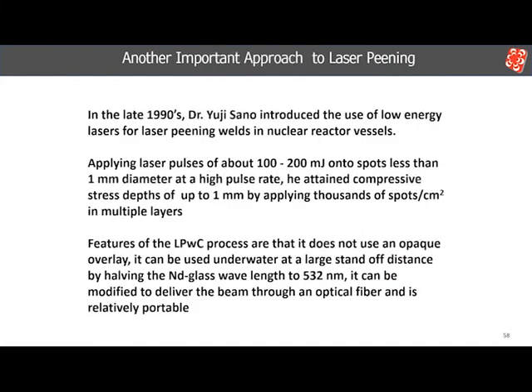In the late 1990s, Dr. Yuji Sano introduced the use of low-energy lasers for laser peening welds in nuclear reactor vessels. Applying laser pulses of about 100 to 200 millijoules onto spots less than 1 millimeter diameter at a high pulse rate, he attained compressive stress depths of up to 1 millimeter by applying thousands of spots per centimeter squared in multiple layers.